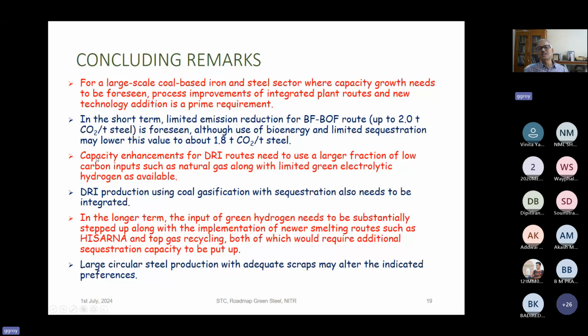Capacity enhancement for the DRI routes needs to use a large fraction of low carbon inputs such as natural gas along with limited green electrolytic hydrogen as available. If we want to make a capacity enhancement in the DRI route, then we have to think of this: low carbon input fuels like natural gas. We have to use it, and we can also supplement it with limited green electrolytic hydrogen wherever possible or available. DRI production using coal gasification with sequestration also needs to be integrated.